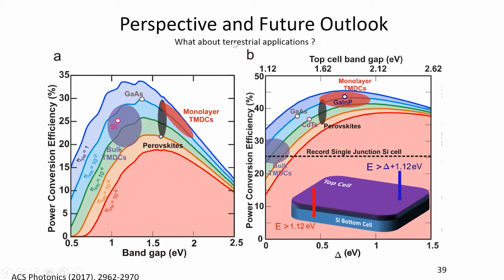So one way to go about terrestrial applications of 2D semiconductors is actually see how you can pair it up with silicon. Again, just like microelectronics, silicon is here to stay even for photovoltaics. The question is, what can you put on top of silicon to make it better or improve the efficiency? And so if you look at the record single junction silicon cell, of course, there is a huge push to integrate III-V semiconductors such as gallium arsenide or gallium indium phosphide on top of silicon because they are very well matched in terms of band gap to give you the maximum efficiency of this tandem cell. Bulk TMDCs are not very well band gap matched. Okay, plus they are indirect, so it doesn't help much.